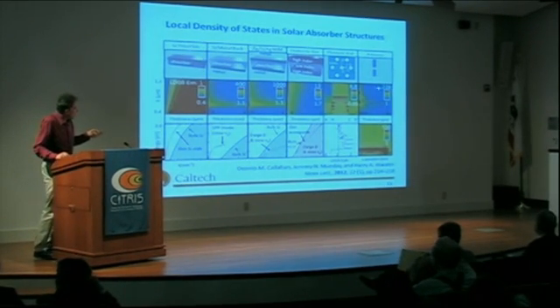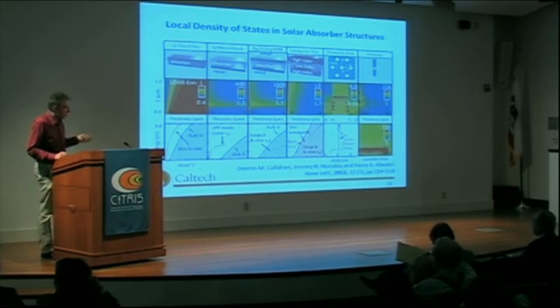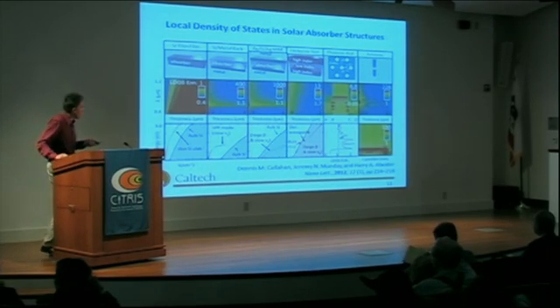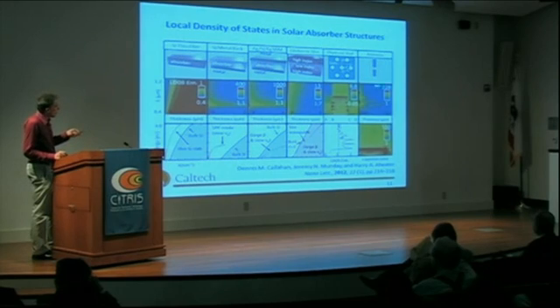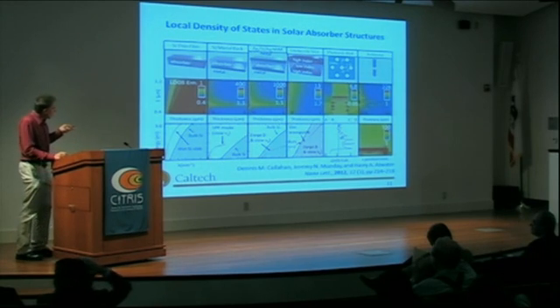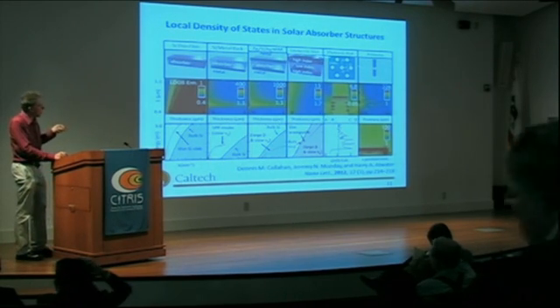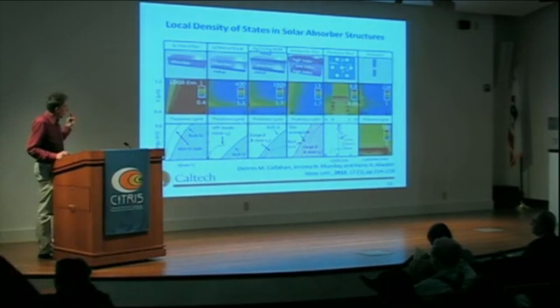And then the final example is that of an optical antenna, which is an object that's received a lot of attention. In fact, Eli himself is actively working on optical antennas at the moment. And you can find that within the gap of an optical antenna, you can also have this enormously greater local density of states. So I would suggest that these are all motifs that you could think about for greatly enhancing the local density of states, the absorption, and then also importantly, the spontaneous emission in these kinds of semiconductor structures.